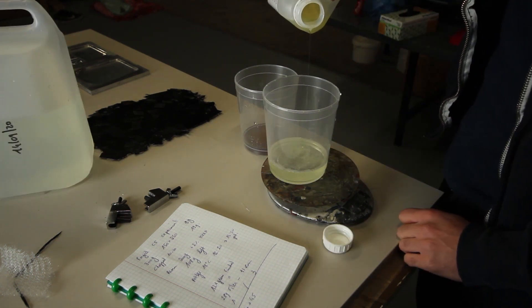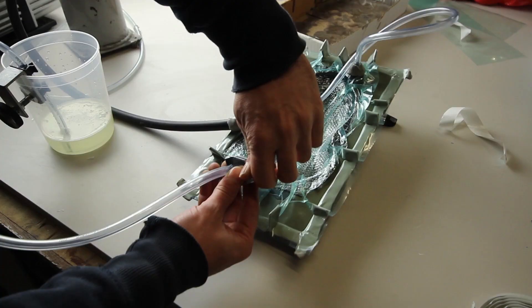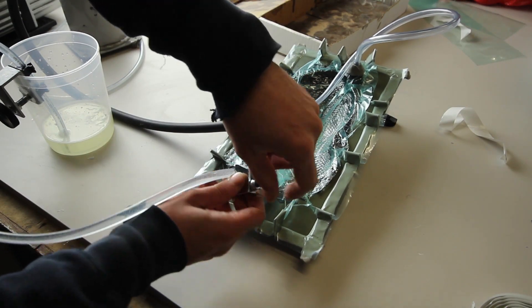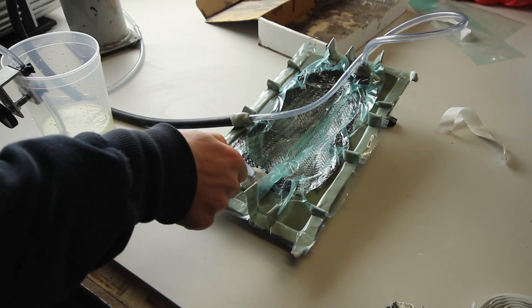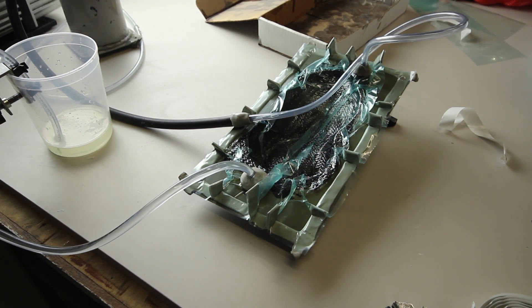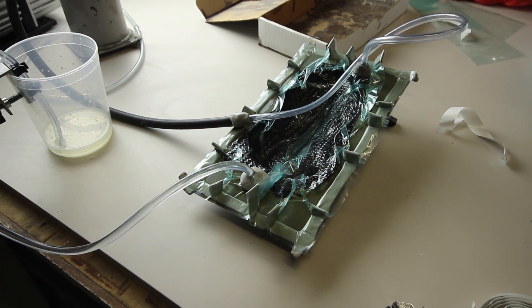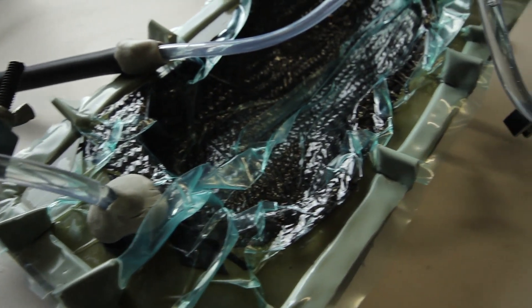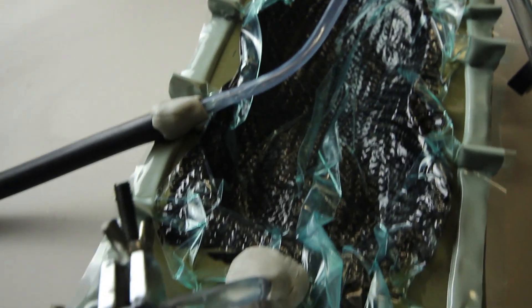I'm mixing some IN2 infusion resin with the fast hardener. You can find all the products in the description down below. I'm using the fast hardener - normally I don't use it on bigger parts, but this is quite a small part and I knew it would infuse quite rapidly. I also didn't degas the resin before doing the infusion. Normally on like if I'm looking for very good parts I always degas the resin to remove any bubbles from the mixture, but as you can see next in a few shots that will be coming, the part is flawless and perfect.